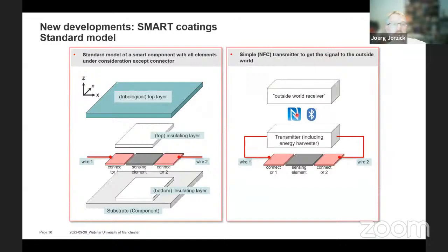So how does it work? So again, we start with a component itself as a substrate, and then we have our sensor coating. Basically, this is also a kind of carbon-based coating, because carbon-based coatings are also kind of dielectric. They have some dielectric property or piezoelectric properties. So by applying a force or current, you will get a response from the system, which can be measured. So we connect this via wires, and then we can read it out in a classical connection, or we can use a transmitting device which can send then the data outside.